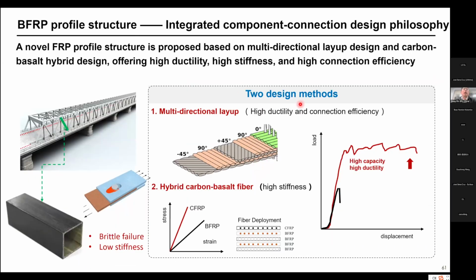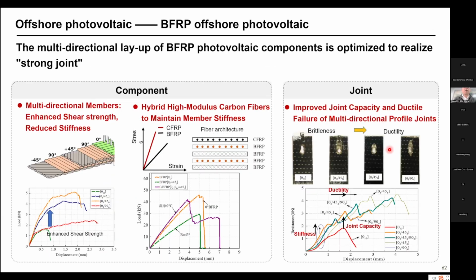Okay, another type of product is profile. Profile can be used to build truss bridges, but the conventional FRP profile may have some problems, like brittle failure and relatively low stiffness. So we use a multidirectional fiber sheet design to make this pultruded FRP profile resist shear and enhance its connection behavior. And also by using the hybrid method, like carbon fibers, to enhance its stiffness. Because after the multidirectional design the stiffness will be lower, so we can balance the loss of stiffness and also achieve high shear capacity. Okay, so test results also demonstrate the shear strength of the composites.